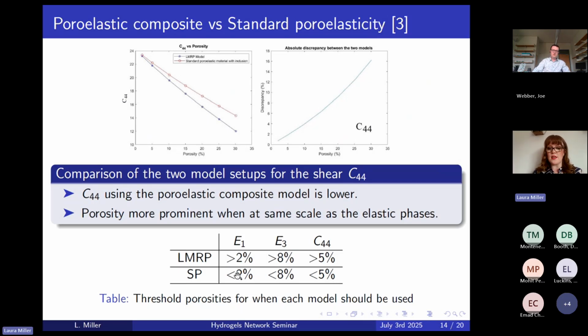If you go beyond 2% though, you're much better off using our new model, because that's the one that will predict the behaviour more accurately. And similarly for E3, you get a bit more leeway, up to 8% porosity, and with C44, you get up to 5% porosity before our model takes over and provides a better and more realistic representation of your tissue.